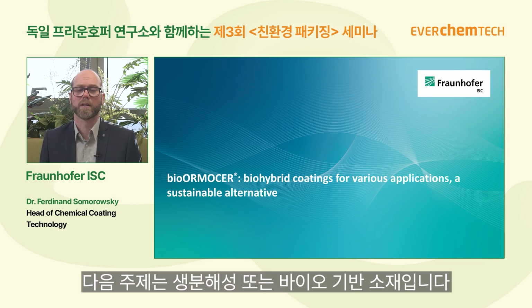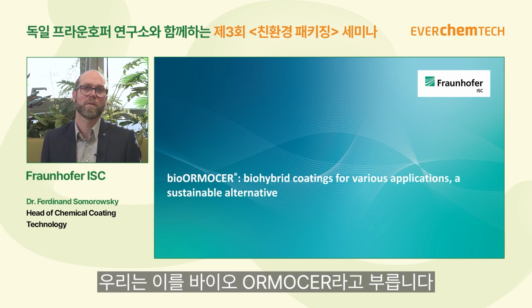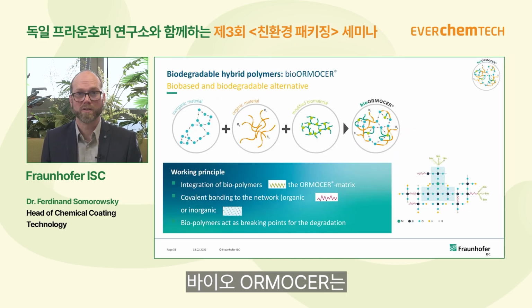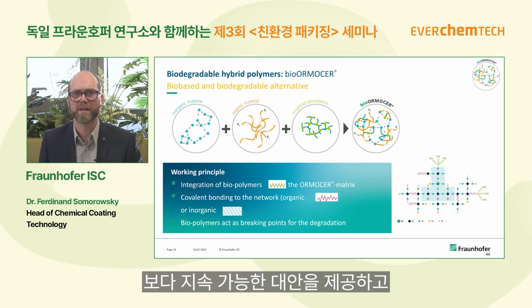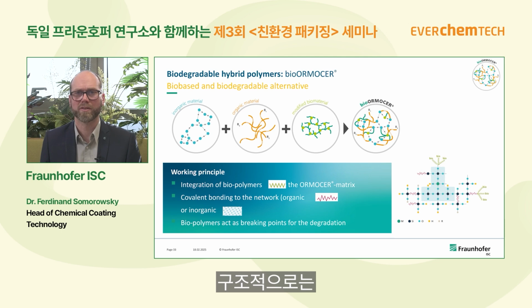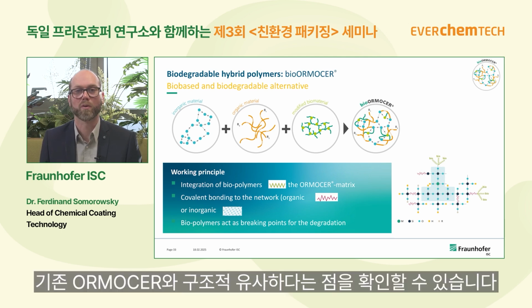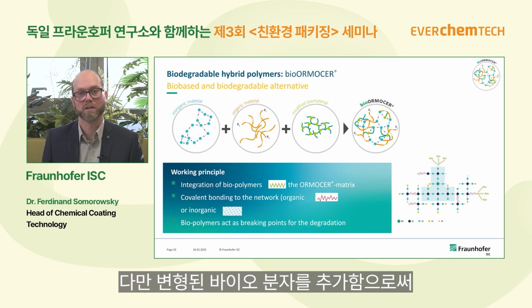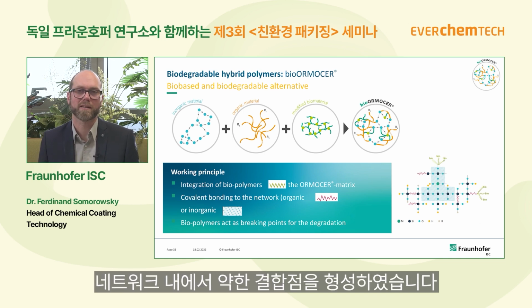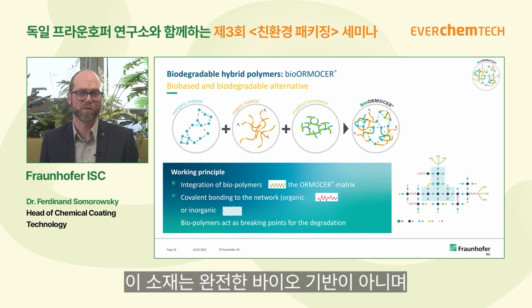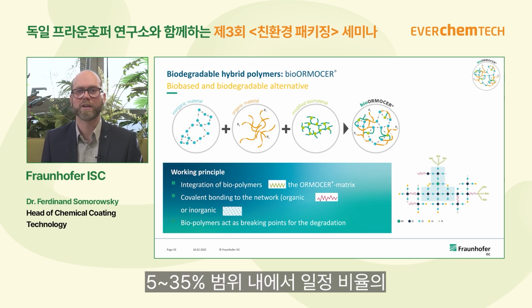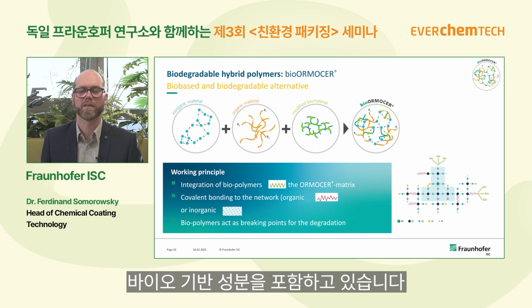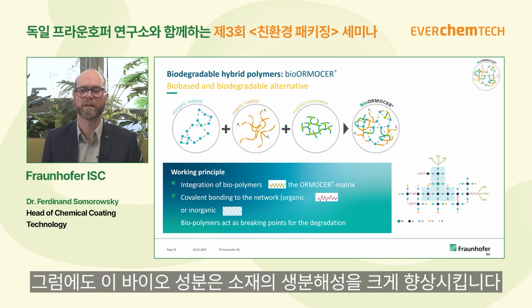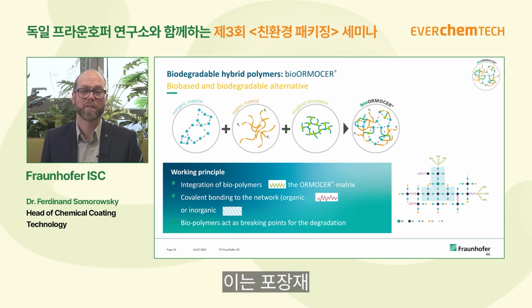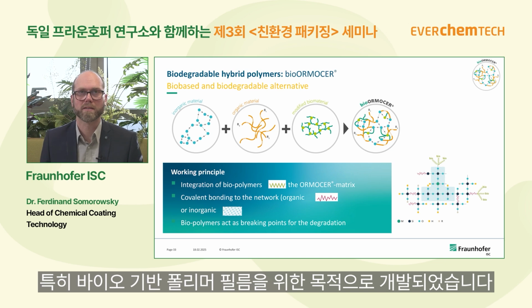When I come to the next topic, biodegradable or bio-based materials, we call them bio-Ormocer. Then I would like to come to the bio-Ormocer. That's a more sustainable alternative for the Ormocer. And when we look at the structure, everything is correct of what you also already saw about the Ormocer. So in principle, the same basic information, basic structures, but here we add additional modified biomolecules, and these biomolecules act like breaking points in a network. So the material is not fully bio-based, only a certain ratio is bio-based, from 5 to 35% in that range. But it helps a lot and helps also degradation of the material. It was developed for packaging materials, especially for bio-based polymer films.